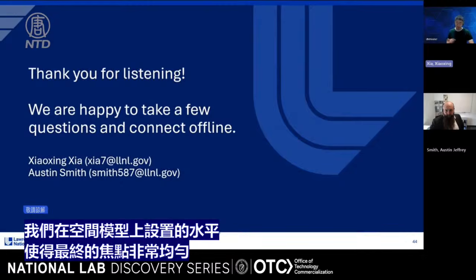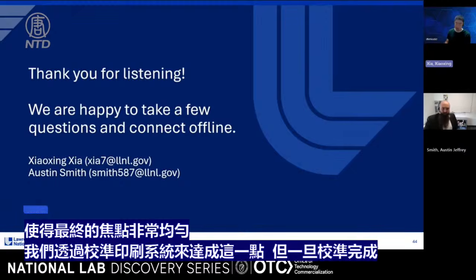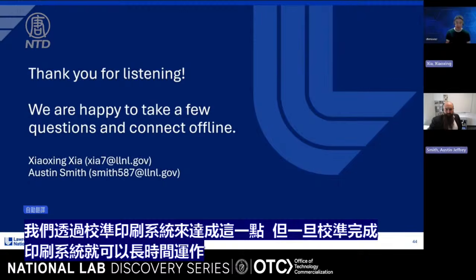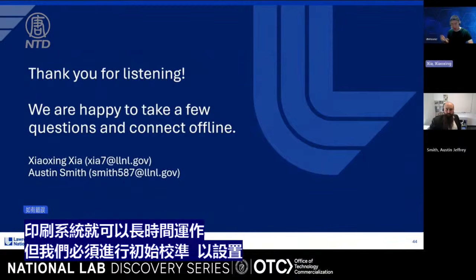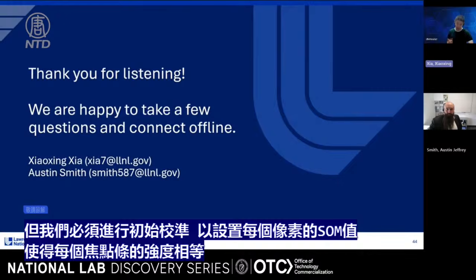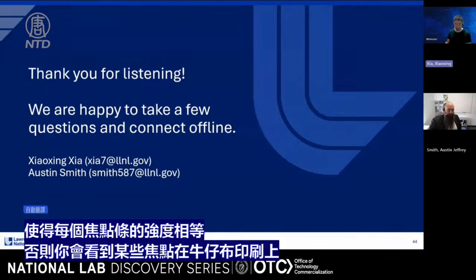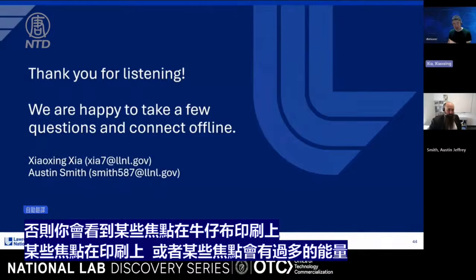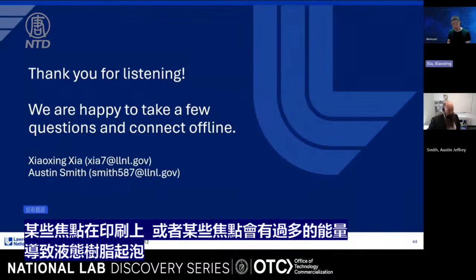And we do it by calibrating the printing system. But once you calibrate it, the print system can operate for a very long time. We have to do an initial calibration to set the SLM values on each pixel such that each focal spot is of equal intensity. Otherwise, you would see some focal spots don't print, or some focal spots have too much power and will bubble in the liquid resin. So the spatial light modulator is a very important aspect.